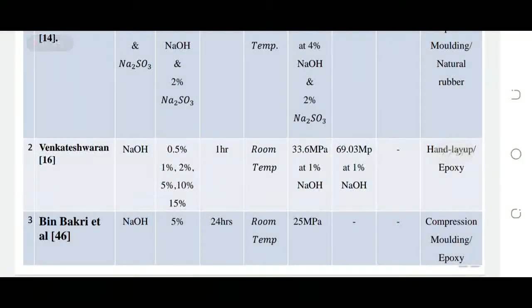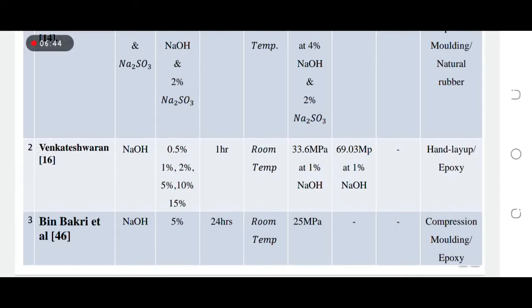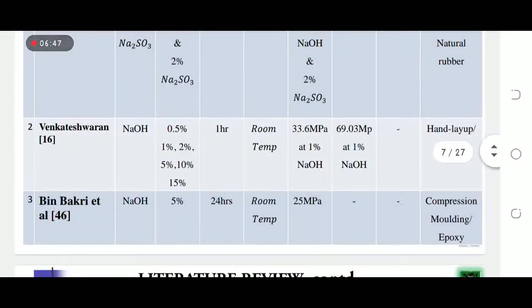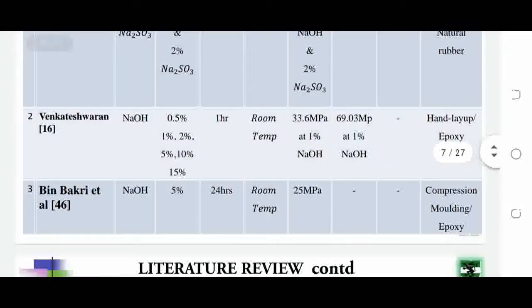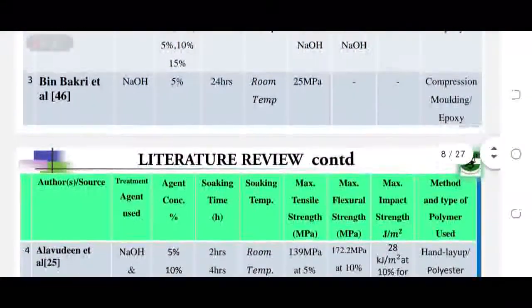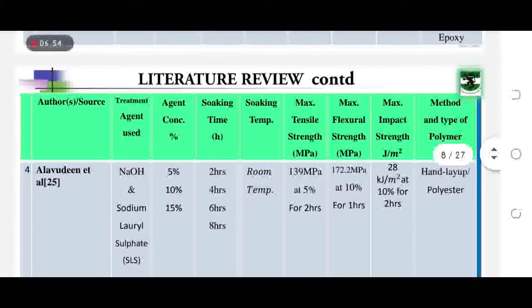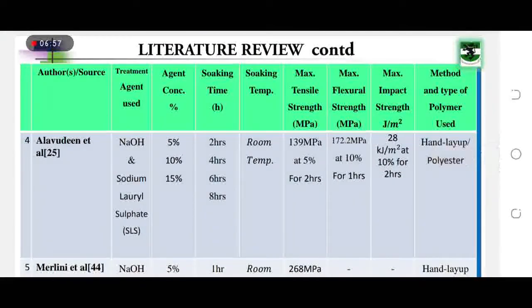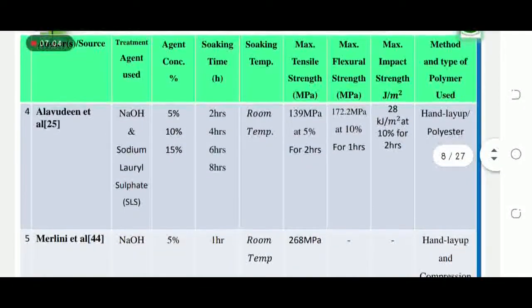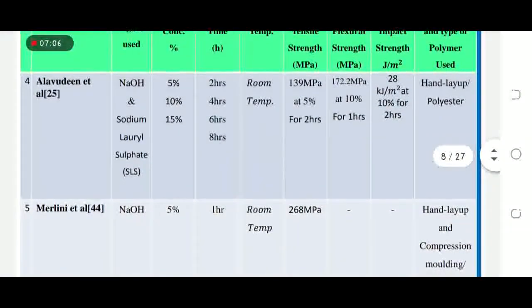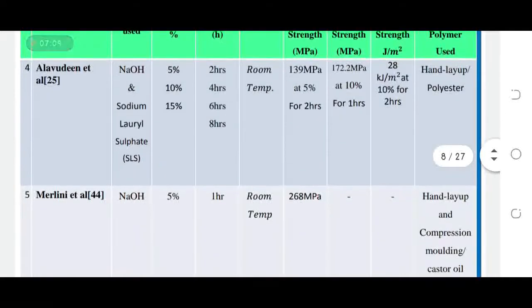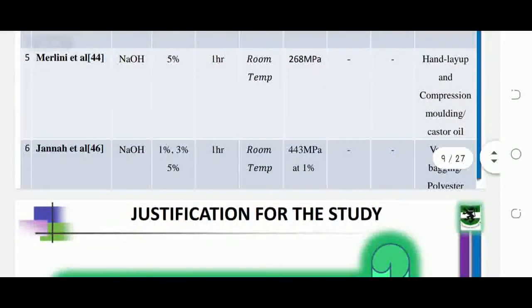Bin Bakri et al. did the same thing with 5% and treated for 24 hours, using epoxy for this and compression molding in fabrication. Alavudeen et al. did the same thing, that is concentration of 5%, 10%, and 15%. Then Merlini et al. studied with sodium hydroxide, treated at 5% for 1 hour. Jannah et al., these are the parameters he used.